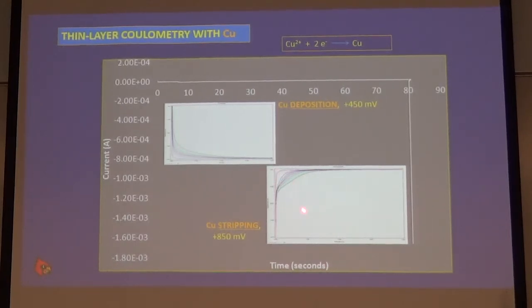When we look at the stripping signal, the signal that we're getting also increases with copper concentration. That's fine. But one thing you cannot possibly see from where you're sitting is the time scale here. This time scale is a minute or two. This time scale is less than a second. The stripping occurs much faster. Well, why is that? It's not a mass transfer related process. All the copper metal is sitting on the electrode. All we have to do is apply potential, and it gets oxidized essentially instantly.